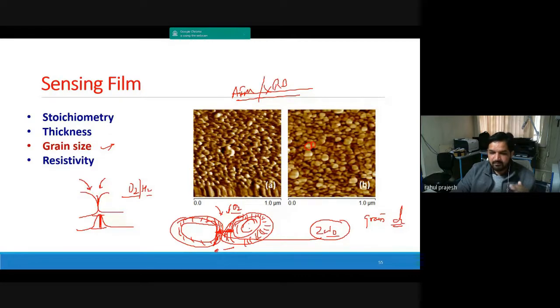So the optimum result will be attained when you have grain size somewhere in the range of twice of the lambda d. Okay, and this is called as a Debye length. So first you need to calculate what is the Debye length for your particular material and that gas combination. Based on that, you should target the grain size. Then you'll get the best response of your material.